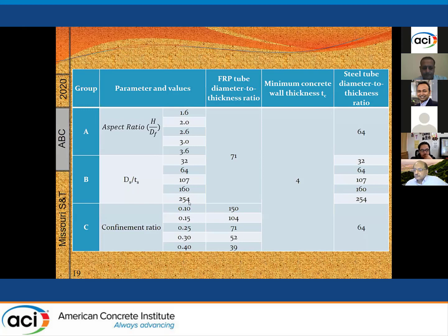If you are working with concrete-filled steel tubes, you probably know 64 is probably the right range. However, on this one, we just would like to see a wide range of parameters. So we went up to 254 to see the effect of using a very thin pipe, which we would expect to trigger more local buckling, but we'll see. And then the concrete thickness was the same as before. And as I mentioned here, the steel tube diameter was a parameter.